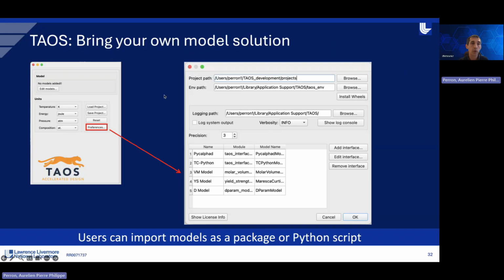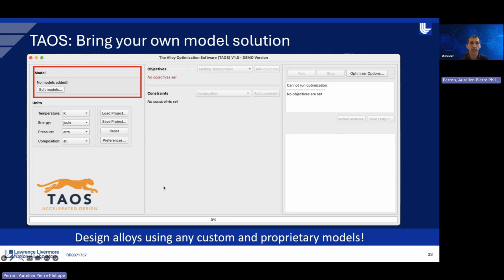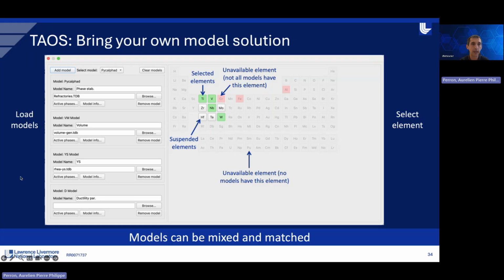So how does it work? Here it's a crop, but on the left side of the TAOS panel, you can go to the preferences and you can directly import Python scripts or Python packages for your model. So here you can see that we had PyCalPhad, compatibility with TC Python, and the different models I was talking about for molar volume, yield strength, and ductility. So once you have done that, you can now load your model for your optimization. This is what I did here. Sorry, I went a little bit fast, but on the left side, I loaded all the different models: the CALPHAD database for phase stability, the database for molar volumes from the literature, the yield strength, and the ductility one.